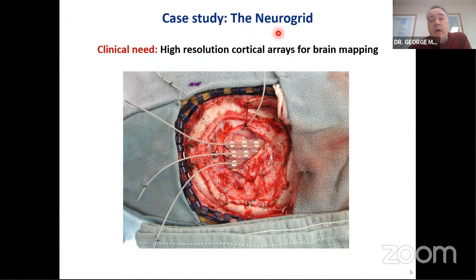So the first example is what is today called the neurogrid, which is a very high resolution cortical array for mapping the brain. Now, this is a well-identified clinical need. This is the current clinical standard for mapping the brain. You use arrays that have quite large electrodes, many millimeters in diameter, made out of platinum, that are inserted under the dura in order to map activity on the brain. And the spatial resolution is very poor, roughly defined by the distance between the two electrodes here. And it's centimeters because you need to have large electrodes in order to record the very weak signals that emanate at the surface of the brain.